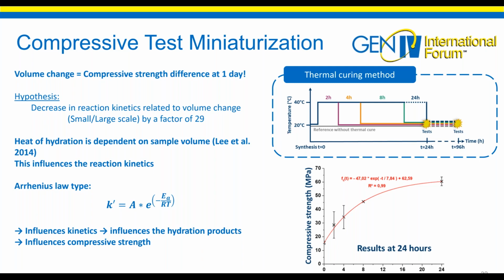To verify this, I set up a thermal cure at 40 degrees Celsius with different times between 2 and 24 hours of cure. All the samples are tested on the same day. Here, the results are obtained at one day. We can see an exponential increase in the compressive strength as a function of the cure time at 40 degrees Celsius. These results allow me to say that a thermal cure of 8 hours at 40 degrees Celsius allows me to have similar results compared to the large scale at 1 day.